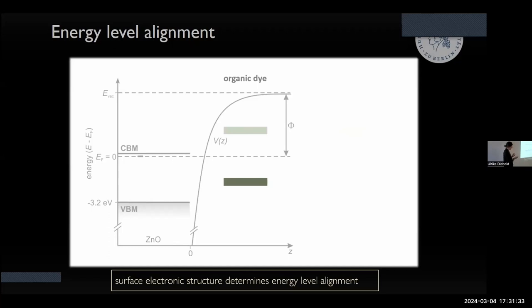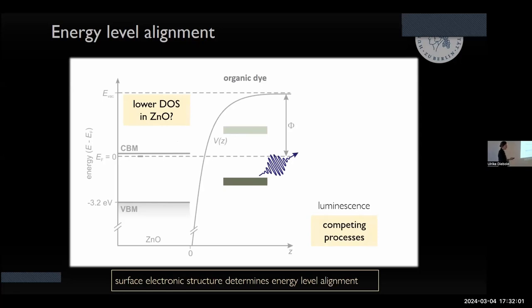separation depends on various factors here. You create excitons in the molecule, and then you can have reduced charge separation because you have a very low density of states or a weak coupling to the density of states. You could have competing processes, maybe in these molecules recombination is very quick, and then you have light emission, or you have charge localization within the molecular film competing with the charge separation, or you can have trap states at the interface in the molecular film.